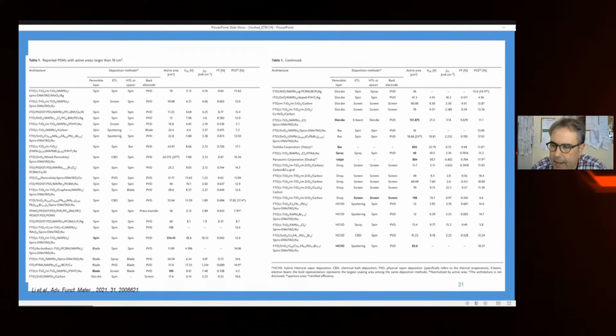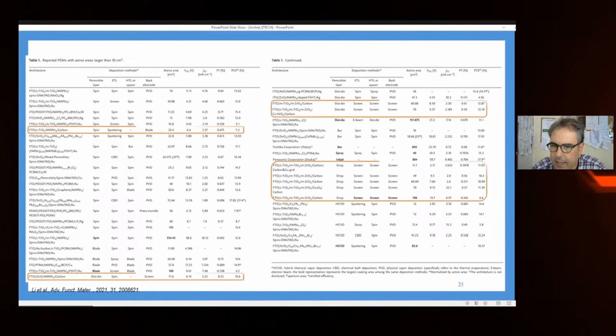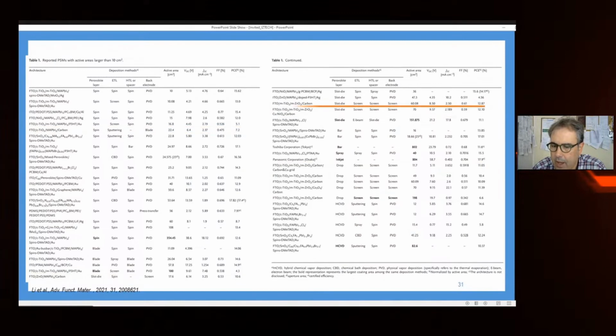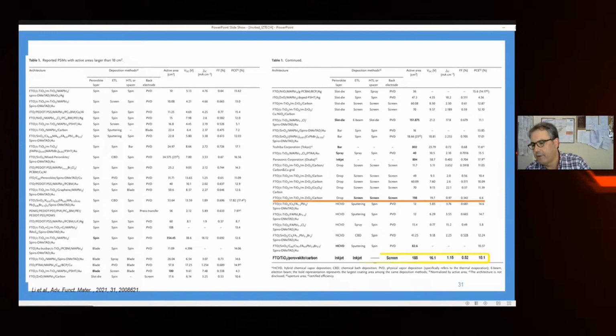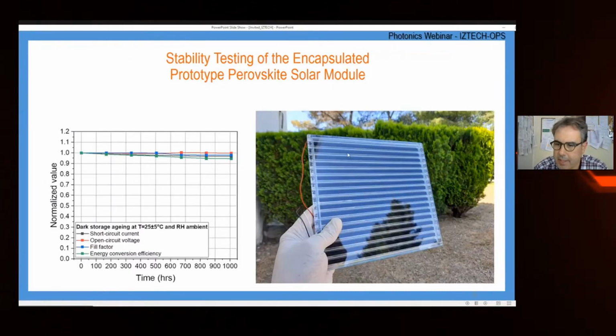If you want to see a survey of the literature, we see that in the case of this method that we follow with inkjet printing, we have perhaps one of the highest performances around the world, in the case that we have the materials without HTM, without any organic materials. This is the perovskite module, with the materials that I said, without any organic materials. The stability also is very good.